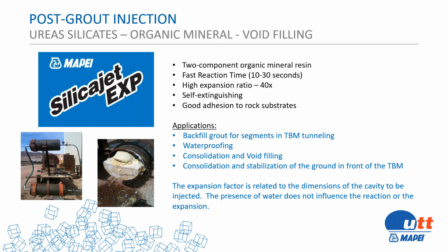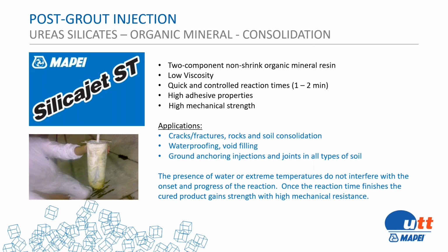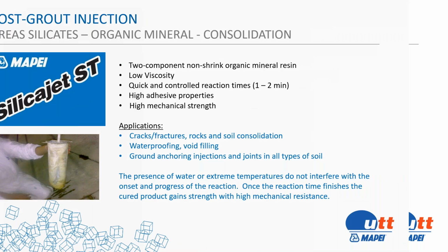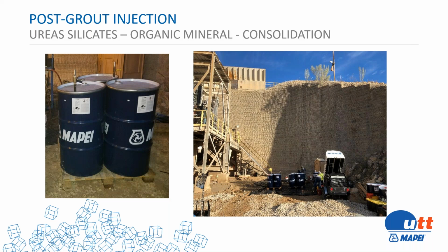Our Silica Jet, again, like our other families, we have 3 different family members of our silicate family. This one is high expansion, 40 times. We use it a lot for backfilling in the tunnels when we're using TBMs. The expansion factor would be relative to the space it's filling. Here we have the Silica Jet ST, which has a very, very high mechanical strength and high adhesive properties. So again, it's targeted for cracks and fractures. Again, you can use it in rocks and soil. So it comes in the drums, and here we have soil where it can be used very successfully in gluing all this rock or soil together. And if there's water, it will cure up and stop the water.